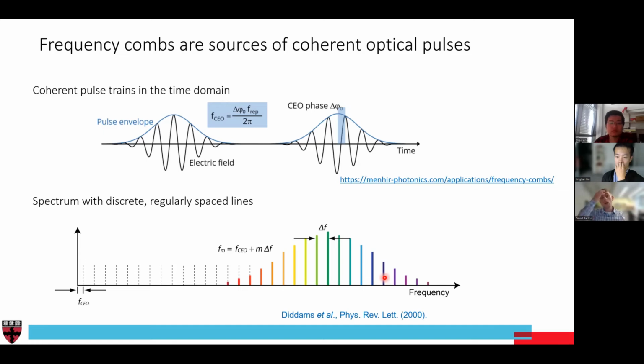To briefly go through this, any pulsed source is actually going to be a frequency comb. If we look in the time domain, we have these pulses that arrive in time that have some given envelope. And if you take the Fourier transform of this, or look at its spectral components, what you find is that these pulses are composed of discrete lines in frequency that are spaced by a well-defined parameter called delta F. This corresponds to the difference in the arrival time between the two different pulses. And then there's one other component, this FCEO, the carrier envelope offset frequency, that defines the phase slip between the pulse here and the pulse here. The field looks slightly different at the peak of the pulse envelope. But with these two parameters, you can define the entire spectrum of a frequency comb.